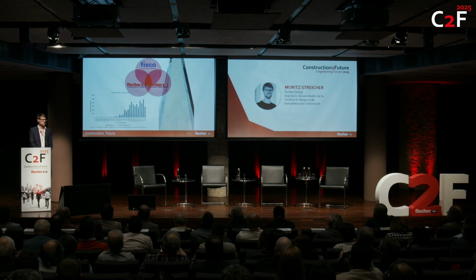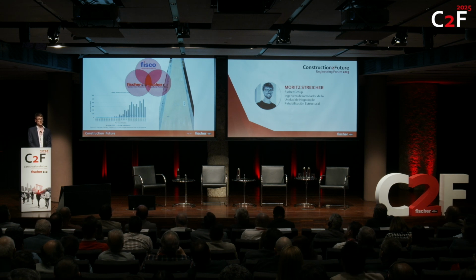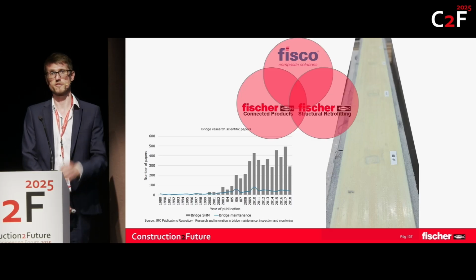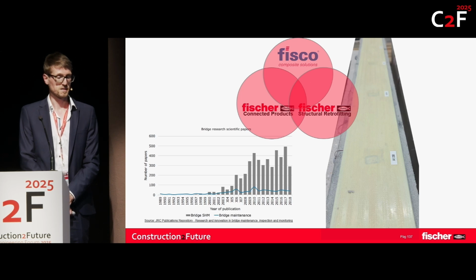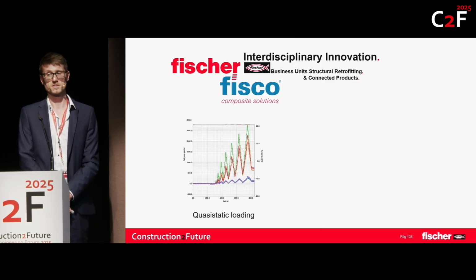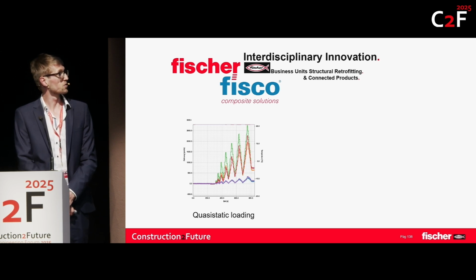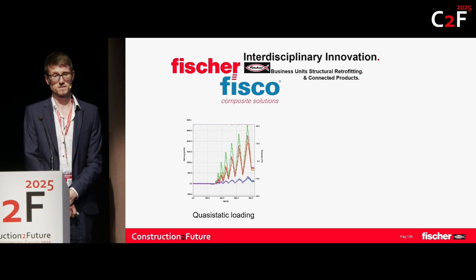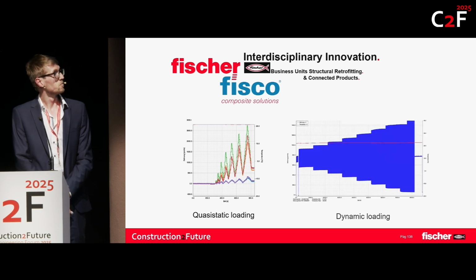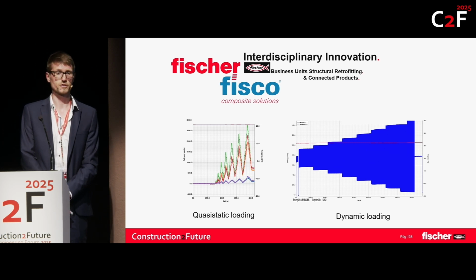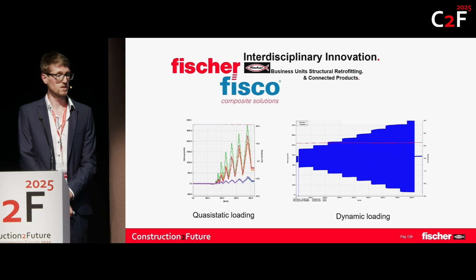And we simply, with Günter's engineers and some help from Connected Products, developed a sensor-integrated laminate. It's still only in a very early research state, which can give you temperature and strain measurements over a longer length of beams and slabs. And it's actually just nice to show that we don't only develop products on our own, but we're also rather well interconnected. And here you can see data on quasi-static measurements with five sensors included in a laminate on a full-scale reinforced concrete beam in 3-point bending. We've also been doing up to 10,000 load cycles on different load levels, up to 75% of the fracture load of the beam, which was way above the normal fracture load of the unstrengthened beam.